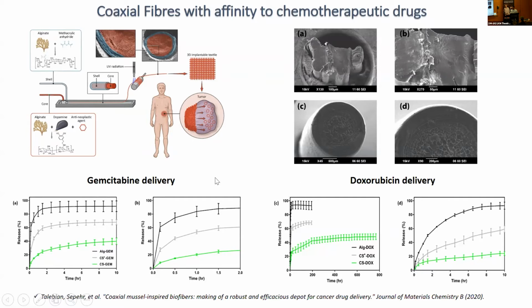Then what we did next was focus on two specific chemotherapeutic drugs that are being used in clinic, one being gemcitabine and the other doxorubicin. We included these drugs in the core section of these fibers, and we measured the in vitro release profiles of these drugs. We also compared these to single fibers made from pure alginate, as well as core shell fibers where both core and shell were made of alginate methacrylate, because we wanted to see the effect of dopamine modified alginate in the core.